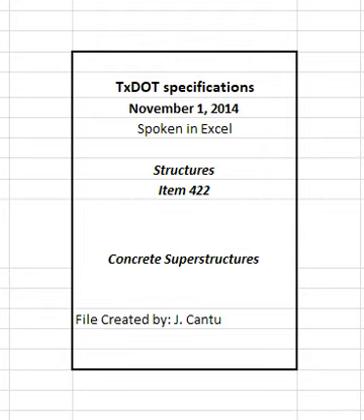When tested in accordance with TEX 436A, revise finishing procedures to produce the desired texture if the texture depth falls below what is intended. Give all concrete surfaces to be covered a lightly textured broom or carpet drag finish when the plans require an asphalt seal, with or without overlay, on the slab. New construction. Provide an average texture depth of approximately 0.025 inches when tested in accordance with TEX 436A.